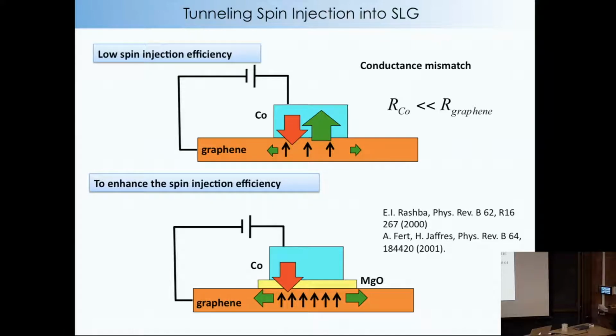Okay? And what happens is, let's say we try to inject some spin. So we're going to inject some spin up. But then once the spins are inside, they could diffuse in all directions. They could diffuse along the charge current. They could diffuse in the other direction. But they could also diffuse back into the cobalt electrode. And sort of the rule of thumb is they'll naturally diffuse to low resistance regions. Right? So since the cobalt is the lowest resistance region, a lot of it will backflow into your injector.